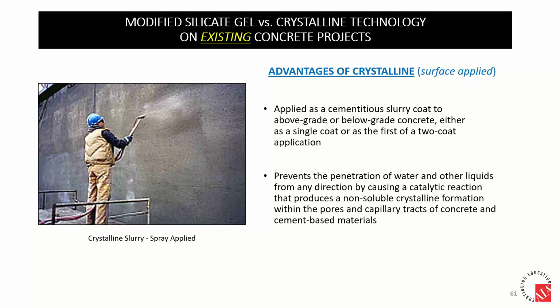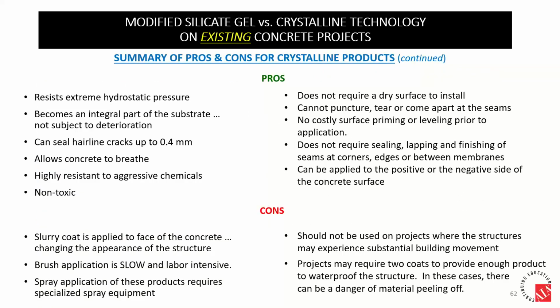Advantage of crystalline is it can be applied as a slurry, above or below grade. It usually is a couple of coats for the application. It prevents water from penetrating, causing a catalytic reaction that produces this crystalline formation that fills the pores and keeps the water out. So, like the silicate gel, resistant to hydrostatic pressure, is integral, can heal some future cracks. It also allows the concrete to breathe, resistant to chemicals, non-toxic. One advantage is it does not require a dry surface like the silicate gel does. Cannot be punctured or torn. No surface priming or leveling. Does not require any finishing. Can be applied positive or negative.